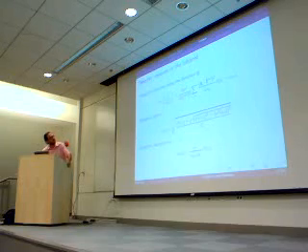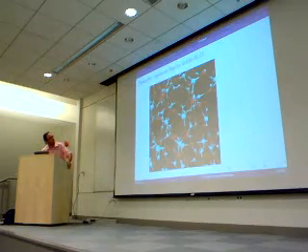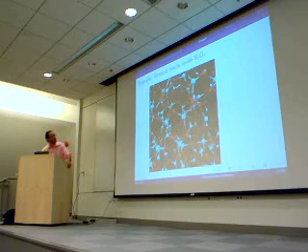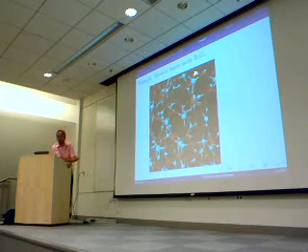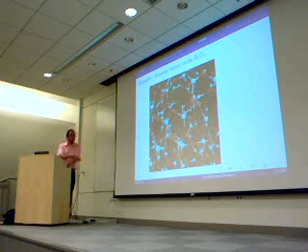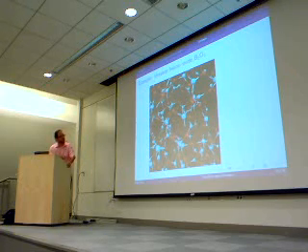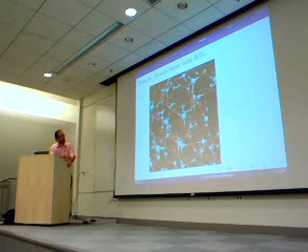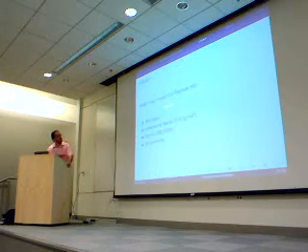Okay, maybe this can be a bit abstract, and I just wanted to give an example of what these spectra look like. This is just what we've done some time ago. This is a model of a glassy material. It was found using Quantum ESPRESSO with Car-Parrinello molecular dynamics, which is something that you will learn next week. This material is formed by these planar units, which in some way also form these rings like this. I think there will be some examples like this in the next week.